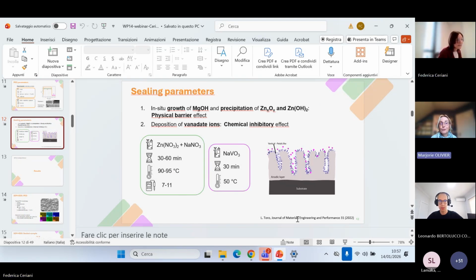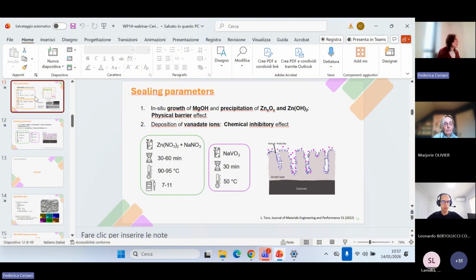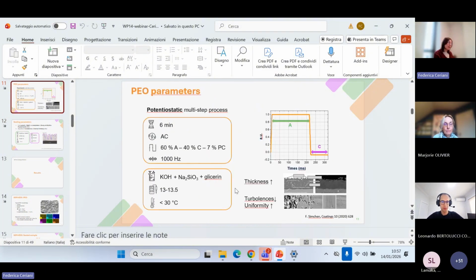Okay, and PEO bath too. PEO bath is 0.2 molar potassium hydroxide with addition of 10 grams per liter of sodium metasilicate and 10 grams per liter of glycerin.